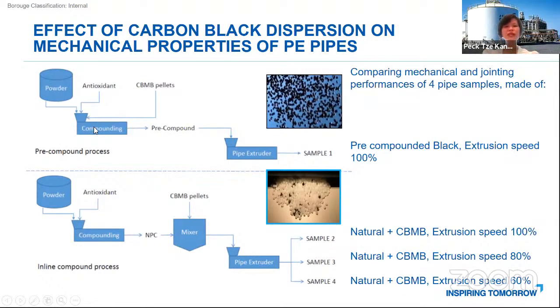did two approaches. One is making our pre-compound the normal way using our big twin screw compounder in our polymer plant, and then taking these pellets and extruding the pipes. We call it sample one. They are made of pre-compound material with the extrusion speed of 100%. We have a parallel comparison of using natural PE material, adding carbon black masterbatch, doing a simple mechanical mixing and putting it in a pipe extruder. And we have samples 2, 3, and 4. They are done with different speeds. Sample 2 has the same speed as sample 1, 3 is 80% of that, and sample 4 is 60%.